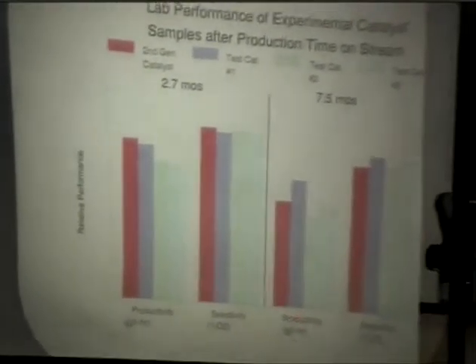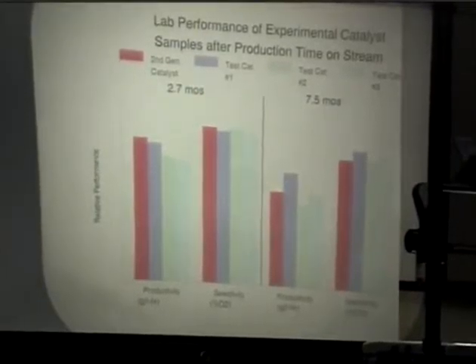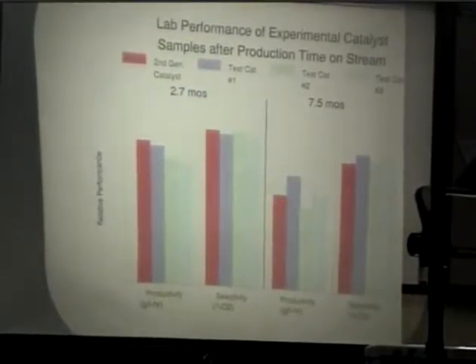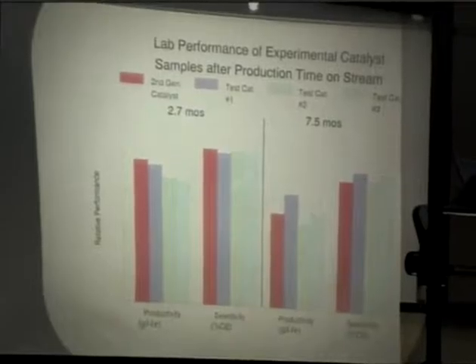But what we were starting to become pleased about is that when we took out that 7.5 month catalyst, the productivity of that test catalyst 1 was greater than our second generation catalyst, indicating that we did have a little bit longer lived catalyst at that point. And the selectivity is improved slightly.